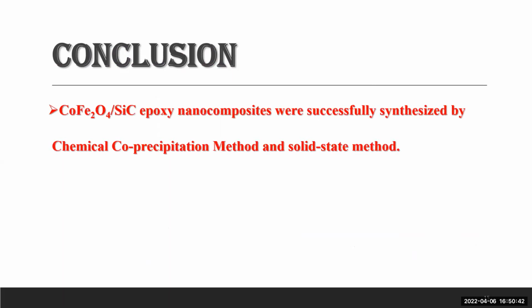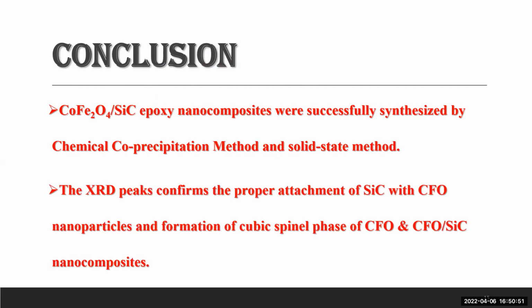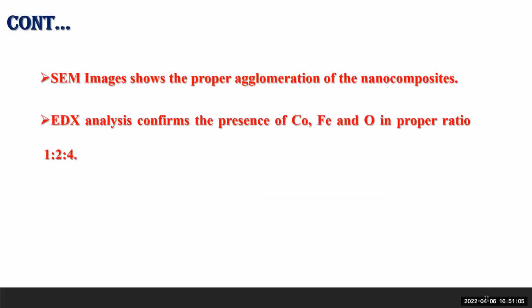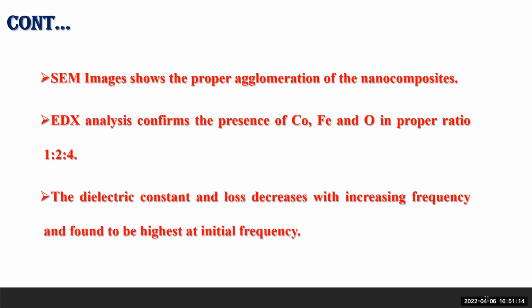Following are the conclusions. Following are the points we have concluded from this work: we have successfully synthesized cobalt ferrite, silicon carbide, epoxy nanocomposite using the chemical co-precipitation method and solid state method, and the XRD peaks confirm the proper attachment of silicon carbide with cobalt ferrite nanoparticles and the formation of the cubic spinel phase of cobalt ferrite and the cobalt ferrite silicon carbide nanocomposite. Then SEM images show the proper agglomeration of the nanocomposite, and EDX analysis confirms the presence of cobalt, iron, and oxygen in proper ratio, that is 1:2:4, and the dielectric constant and loss decrease with increasing frequency and are found to be the highest at initial frequency.